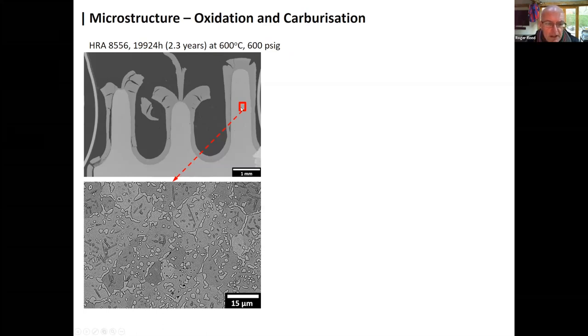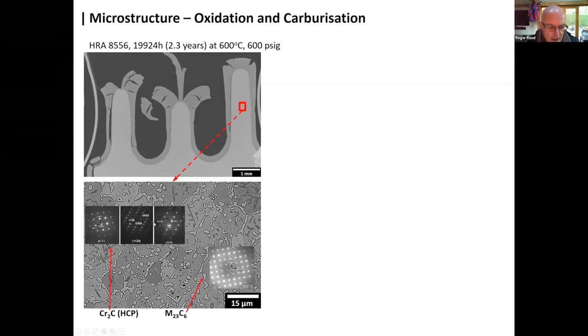And if you look at the microstructure of the fins here, then there is extensive evidence of carbides forming such that the net carbon level is way beyond that which was there in the original steel. And you can prove that the carbide species are the famous M23C6 carbide here, and also some other evidence of chromium-rich hexagonal HCP-type carbides present in the microstructure.